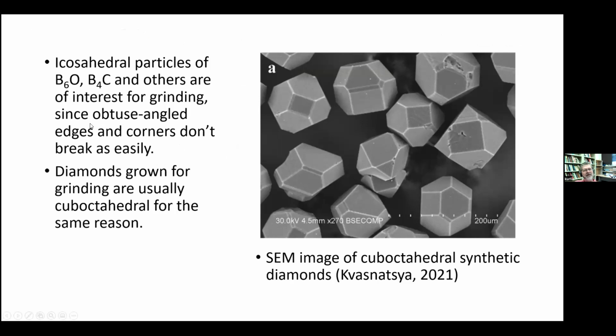in grinding it's preferred to use obtuse angled edges and corners because they don't break easily, and that's why, for example, diamonds, which are one of the most important grinding materials, are grown as cube octahedra, which are shown here, because they last longer. The corners don't break off during grinding as quickly. And all the commercial diamonds, if you grow diamonds at a low temperature, I hope I get this right, you get octahedra at a low temperature, cube octahedra in the middle, and cubes at high temperature, or vice versa. I'm sorry, I should have checked that.